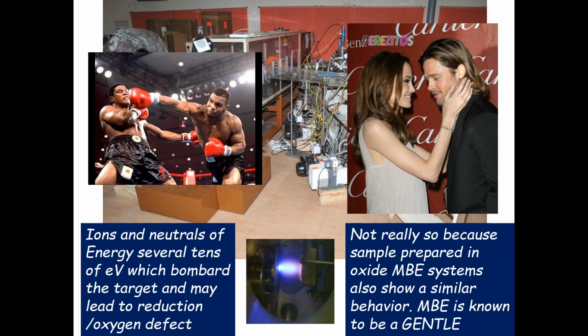But so they say use MBE. MBE is a very gentle process, because when you do MBE, anything that you evaporate comes with a fraction of an electron volt energy, and it lands on the surface very gently. So if you can make a 2D electron gas using molecular beam epitaxy, then we'll see that, yes, there is something happening at the interface. Now people have done this. People have shown that even with MBE, you can make nice 2D electron gas at the LAO-STO interface. So the bottom line is you only have to know how to do your PLD carefully.